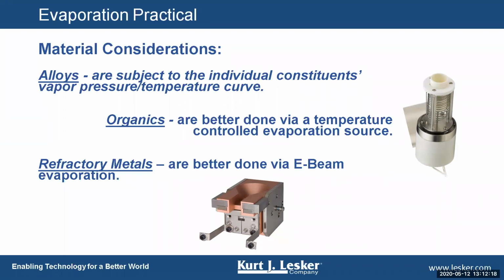Do you have any additional comments on E-beam evaporation of oxide materials? Only the ones that I've covered. Make sure the crucible liner is electrically conductive. Make sure you use as low a voltage as possible in the E-gun. Generally mine can go from 4 kilovolts to 10 kilovolts, and I usually use 4 kilovolts for oxides. And a wide sweep pattern at as large an amplitude as I can afford, and as slow a frequency, because the more the beam crosses the center, the better. Trust me when I say there are pre-programmed center cold patterns, i.e. it doesn't cross the center, but it always crosses the center. No matter what the manufacturer says, and I've tried just about every E-gun under the sun, the beam is always going to cross the center, and that's where I'm going to core drill through on oxide materials.